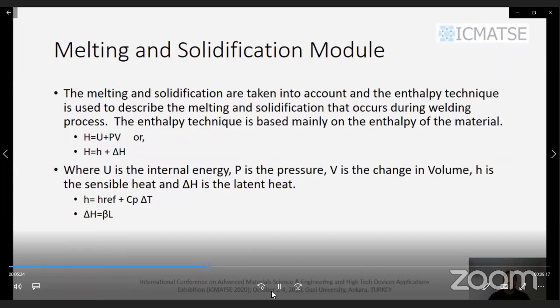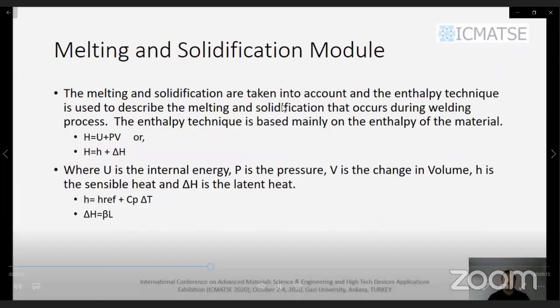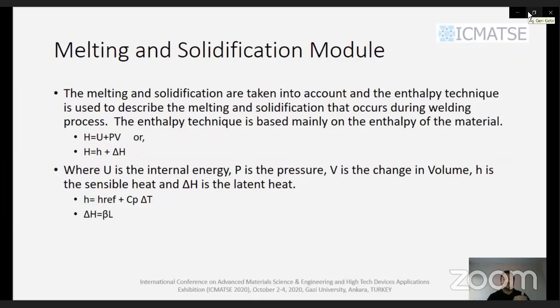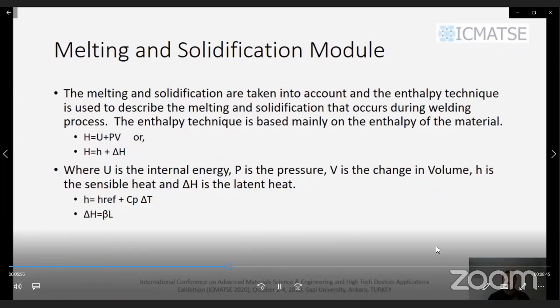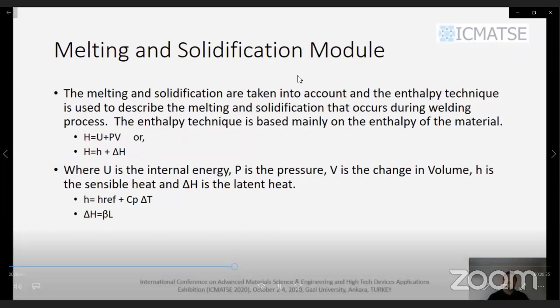Melting and solidification module. The melting and solidification are taken into account, and the enthalpy technique is used to describe the melting and solidification that occurs during the welding process. The enthalpy technique is based mainly on the enthalpy of the material. Here is the equation. H is equal to U plus P times V, or H is equal to minor h plus delta major H, where U is the internal energy, P is the pressure, V is the change in the volume. Then minor h is the sensible heat and delta H is the latent heat.